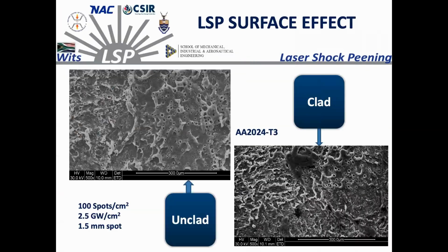When we're comparing what is happening at the different coverage for the Clad and Unclad, for the Clad version, maybe with this light it is not super clear, but there was definitely much more evidence of plastic deformation on the surface. So probably because, again, the Clad is a much softer material, basically a pure aluminum alloy. So mechanically speaking, it's something much, much softer. So in that specific case,